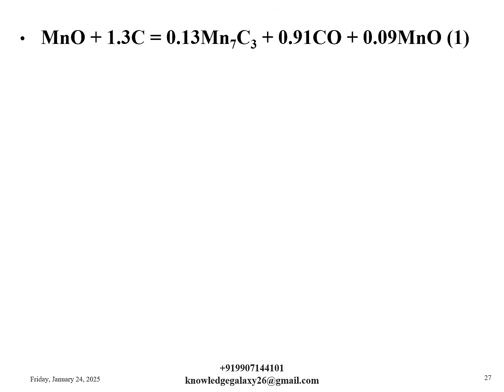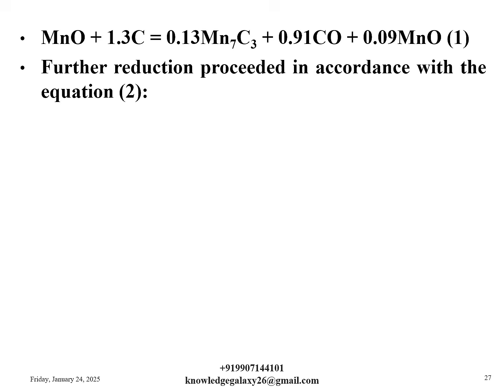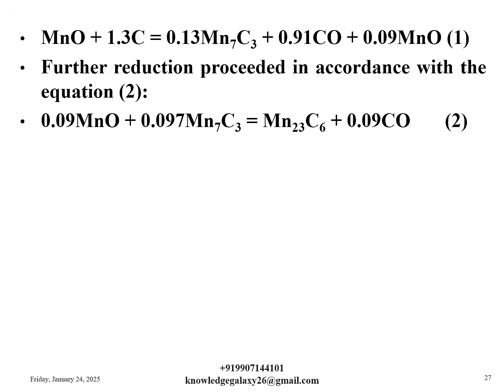MnO, the reaction given is MnO plus 1.3 C is equal to 0.13 Mn7C3 plus 0.91 CO plus 0.09 MnO. This is the first equation. Further reduction proceeded in accordance with equation 2, which is given below. 0.09 MnO plus 0.097 Mn7C3 is equal to Mn23C6 plus 0.09 CO. This is equation number 2.